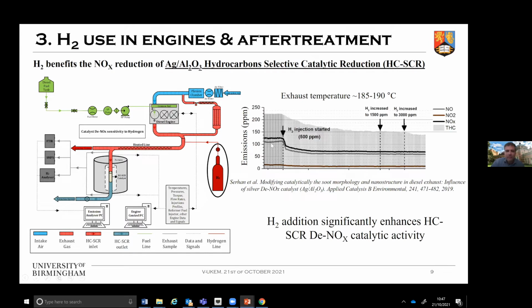So originally we saw at this temperature range around 180, 190 degrees that the catalyst activity was not very high when it was fed only by hydrocarbon. However, when we start to inject hydrogen, our catalyst activity was increased. And of course, we could have played here trying to optimize the process between how much hydrogen we can add and how much would be the hydrocarbon NOx ratio to try to make the catalyst as efficient as possible.